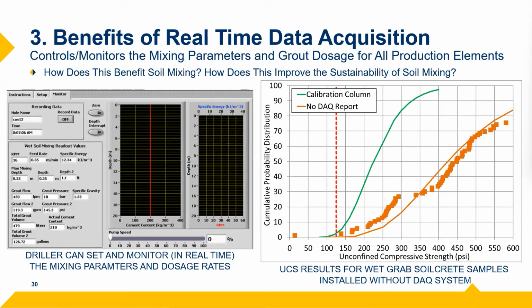And so what I'm showing here is a cumulative probability distribution curve. I've taken all of the sample strengths that we've gotten from just our wet grabs, and I've plotted them here to say, okay, our specification for this particular project wants us to have a certain average value or a 50% value and a certain 90% passing or 10% failing under value. So here you can see arbitrarily it was set at about 130 PSI for this particular project. And you can see that our 10% under or 90% passing was about 220. So we're a little bit higher.